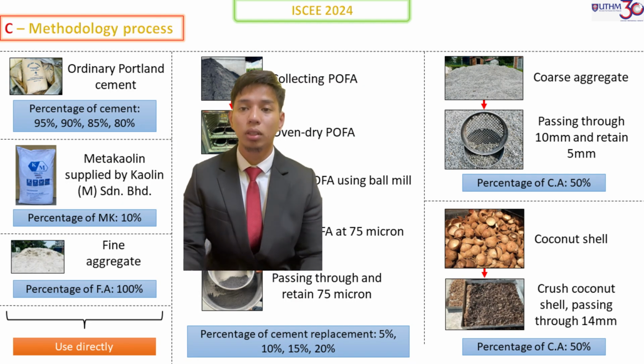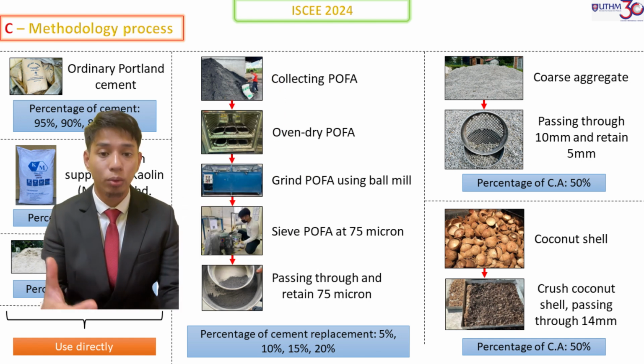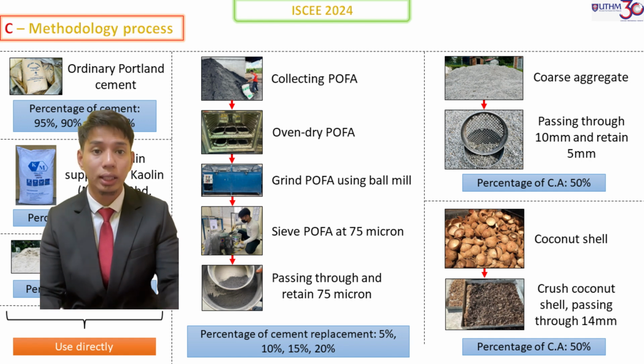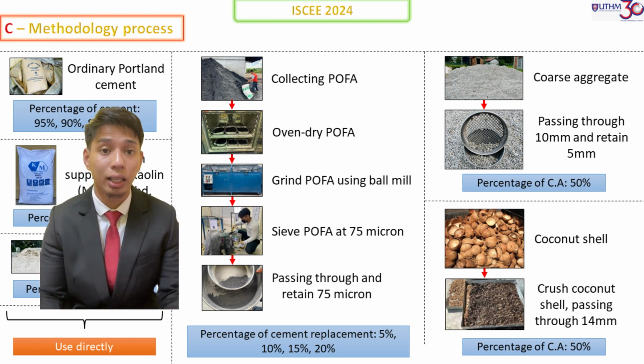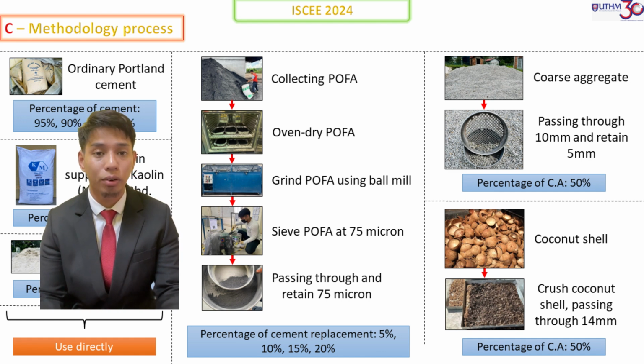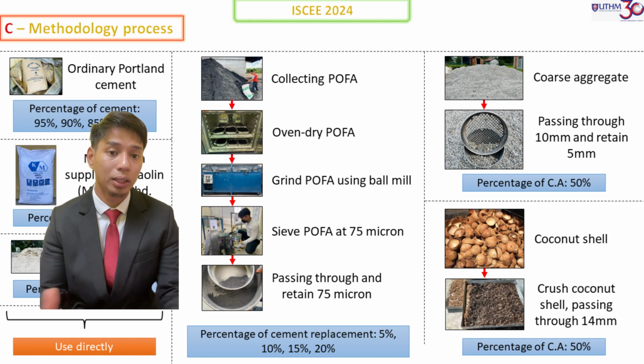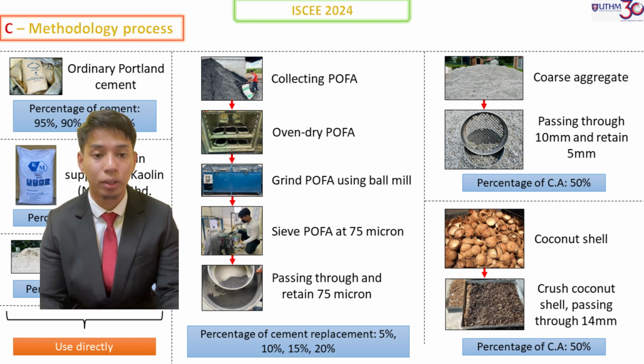So this is the methodology process. For ordinary Portland cement, the cement content used is 95%, 90%, 85% and 80%, which I will replace with POFA. As we can see in the slide, I collect the POFA and oven dry it, grind POFA using the ball mill, sieve POFA, and lastly pass it through the 75 micron. The POFA content used is 5%, 10%, 15% and 20% as a cement replacement.